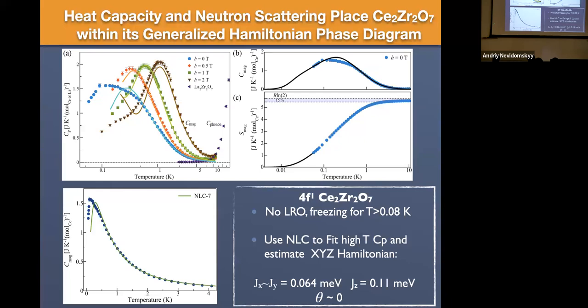But the reason it's a peak here is just the scale of the exchange interactions. They kick in somewhere around here. They start to have an effect somewhere around here, and the heat capacity and the entropy have to go to 0 at 0. So that's why there's a peak in between. So you can basically say it's establishing some sort of quantum coherence, right? About the temperature for the peak. You could make that sort of argument.